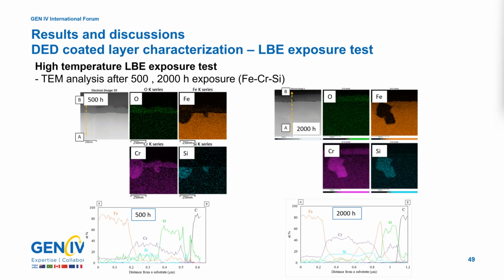The iron chrome silicon coated layer forms an oxide layer with an outer composition of chrome oxide and iron oxide, and an inner layer of thin and dense silicon oxide, which leads to higher corrosion resistance.